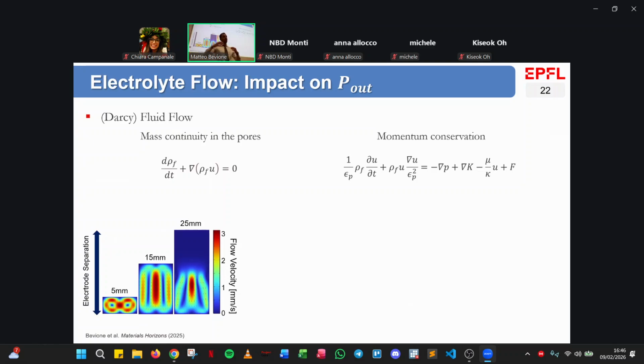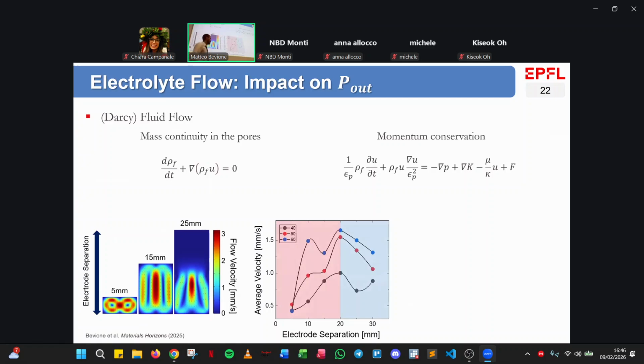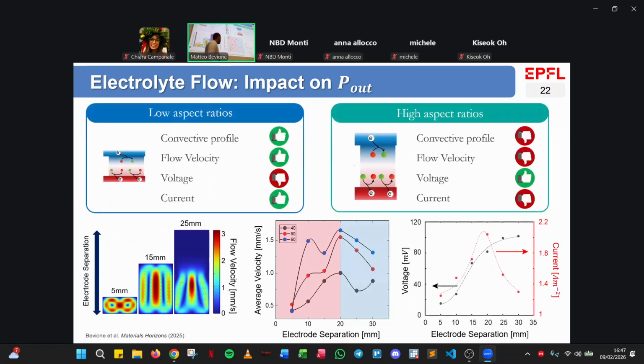But if we stretch the electrode separation too far, then we will not have enough thermal power to close the convective cell. And at that point, the velocity of the species close to the electrode, as you can see in this graph here, will just decrease. And if it decreases, you cannot really have new species at the electrode as fast as you want. So here it's shown that the voltage fundamentally keeps increasing because your temperature difference keeps increasing, but it's all about the current. It's really all about the current. So you need to find a sweet spot, depending on the conditions you have in the surroundings, to produce the largest power output you can.